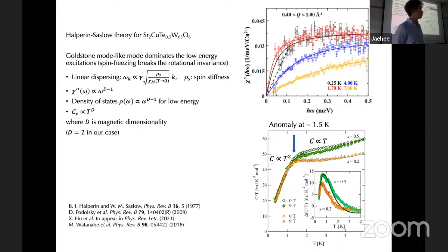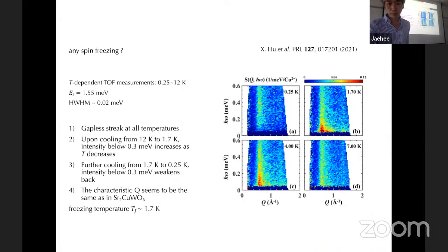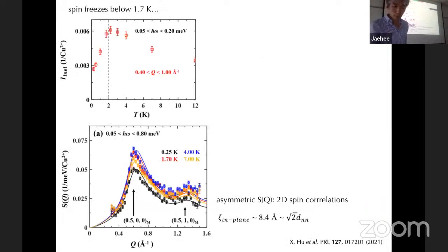And you're promising to tell why this coupling to the third dimension is so ridiculously small that one can neglect it. Oh yeah. Can you maybe show that again? Right. For instance, when I do this, we fit the data, this S(Q). If it's three-dimensional, this will be isotropic, and so we also estimated this out-of-plane correlation is basically zero.